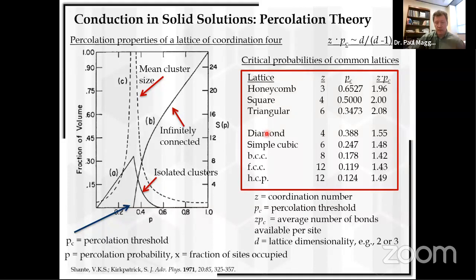So for example, for an HCP type structure, which has a connectivity of 12, you hit that threshold at only 12% substitution. Whereas for the diamond lattice, which has a connectivity of 4, you need to put in around 38.8% substitution before you have a connectivity throughout that material. So if you have a diamond structure, it takes a much higher amount of substitution to hit that threshold versus something with a much higher connectivity.